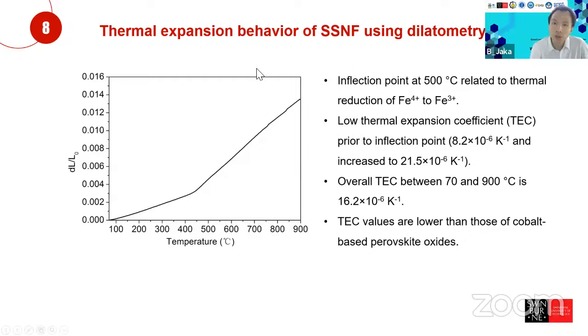Okay, so then I continue into the thermal expansion behavior using dilatometry. As we are heating at high temperature, we need to be careful with the expansion of our cathode as well. So we need to check the thermal expansion coefficient of this cathode material. We subjected this material to dilatometry, and we find that there are two different regimes of expansion. The first one is below 450, and the other one is above 450. As you can see, the slope is quite different in these two regimes, right? And the overall TEC is 16.2 × 10^-6.